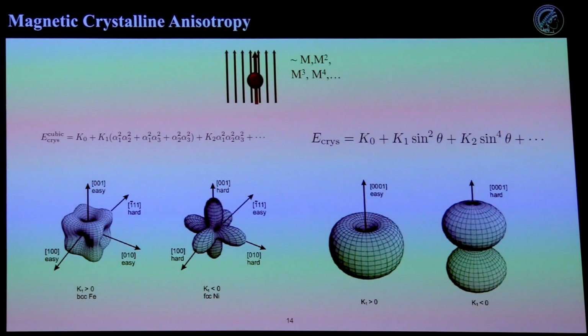The magnetic crystalline anisotropy is actually probably one of the more important things in stabilizing skyrmions. So in the B20 compounds, you usually have anisotropies that look something like this. You have this cubic anisotropy that either has an easy plane or an easy axis. So for iron, it's this easy axis. It likes to go on 0, 0, 1, the 1, 0, 0, and the spins can point in any direction. They're all the same energy.